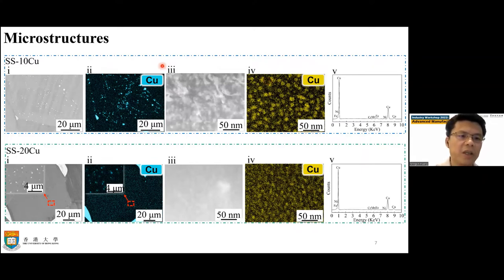Basically, if you look at the microstructure with 10% copper, you will see that all these white dots are copper precipitates, okay? This color here represents the copper. You also see the X-ray, these are EDX. For the EDX, you also see this copper here. So clearly we have this copper precipitation in this stainless steel. In the normal stainless steel, you do not have these copper precipitations, okay? For higher copper contents, we are going to see more of this copper precipitation. So basically, we change the microstructure of the steel.